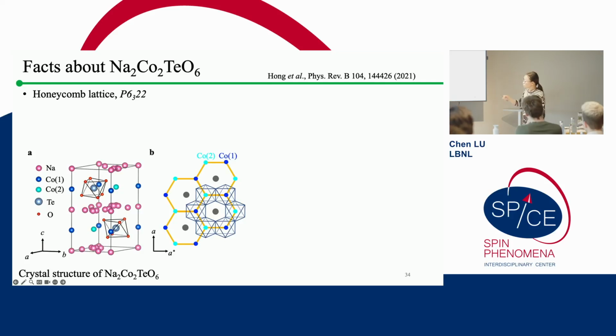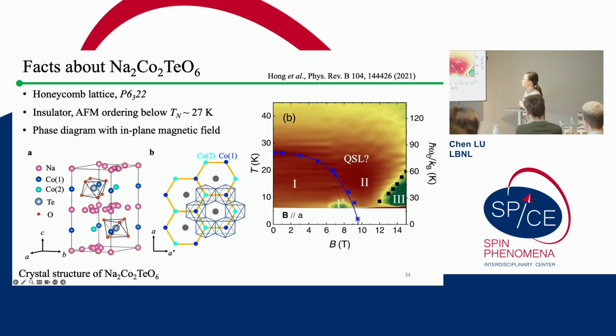First of all, this sodium cobalt tellurate hosts a very similar crystal structure compared to alpha ruthenium trichloride. For alpha ruthenium trichloride, it's the ruthenium atoms that give you this so-called honeycomb lattice. But for this one, it's actually the cobalt atoms that form this honeycomb lattice, which is important for the Kitaev physics. Okay. And the other thing is this material is also an insulator, and it goes into the antiferromagnetic order phase below about 27 Kelvin, which is higher than alpha ruthenium trichloride, which is only 7 Kelvin.